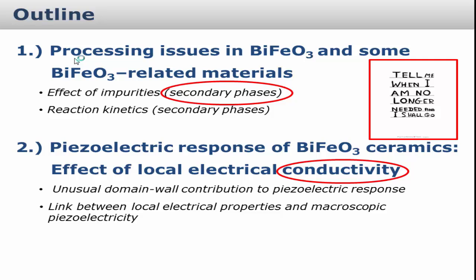I will concentrate here on just one specific issue, that's conductivity. I will not talk about conductivity in terms of a conductive path that goes through the whole sample, but I would like to stress certain local conductive paths that do not necessarily percolate the samples. For example, you can have some local conductive paths within grains, and I will show that this may also affect the macroscopic overall electromechanical response, with this example of bismuth ferrite. I think it is important because this effect can also be present in other BiFeO3-based materials.